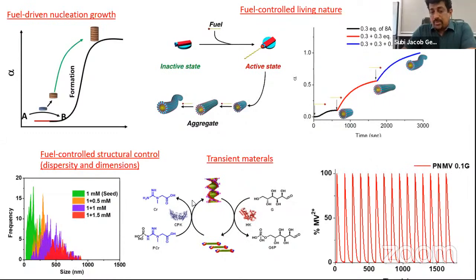You see that this is an enzymatic network. One is ATP getting generated, then monomers. So this is a creatine phosphokinase enzyme, which in situ generates ATP in the system. Then these monomers grow into the fibers. And there is another enzyme in the system, which is hexokinase, which hydrolyzes ATP back to ADP. So by carefully modulating the rates, we can populate this particular assembled state, which is an out of equilibrium state. And we can define the lifetime of that state by just changing the concentration of the system.